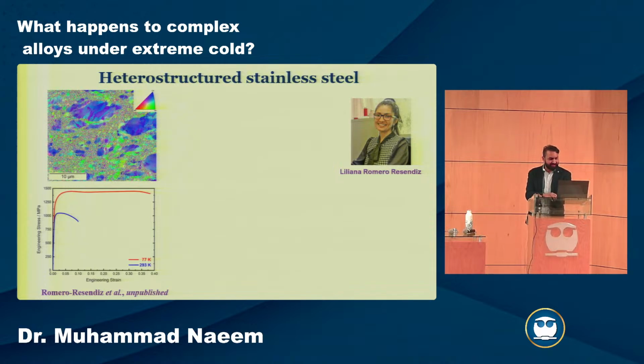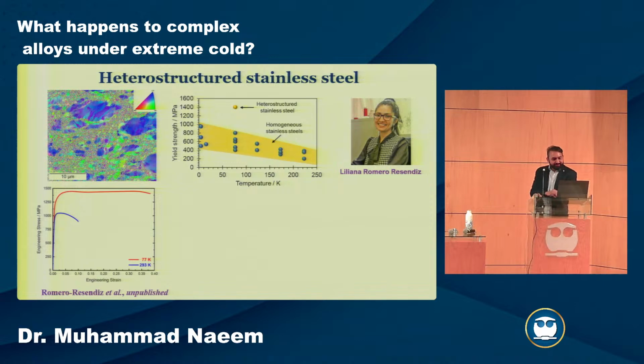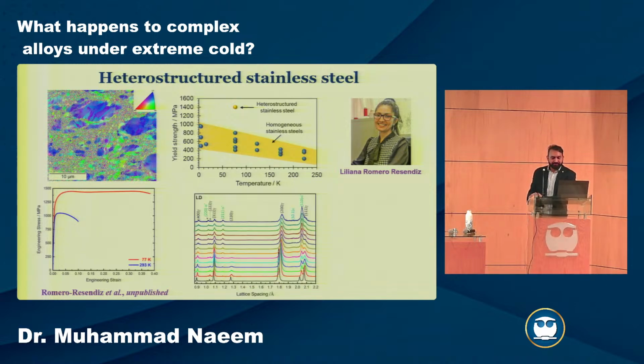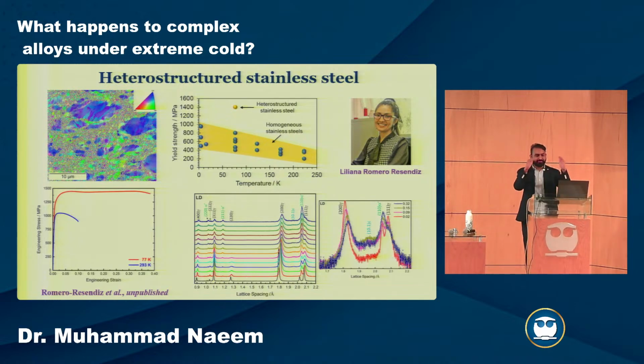Again, this work is not published yet, so it's like a preview. Here you can see a comparison of yield strength of normal steels and here heterostructured stainless steel. It's very high as a function of temperature, and this one is for 77 K. And again, the reason for this is we also did in situ neutron diffraction, and you can see different phases coming out, including HCP a little bit, but then it disappears. You see there is no peak over here, then there is this tiny bump over here, then it disappears again. And then there is also the alpha prime phase. Looking at how it changes with the deformation, you can see how this phase is coming and going, and these two are changing. So alpha prime is forming at the expense of gamma.